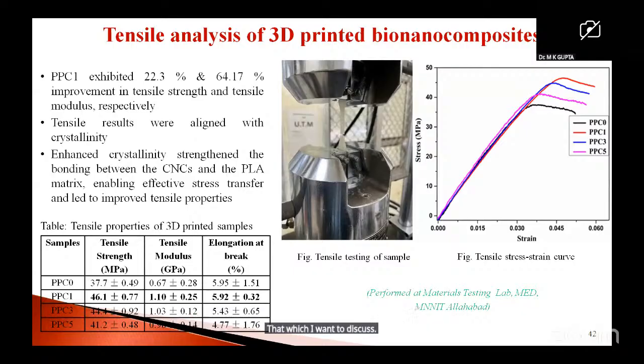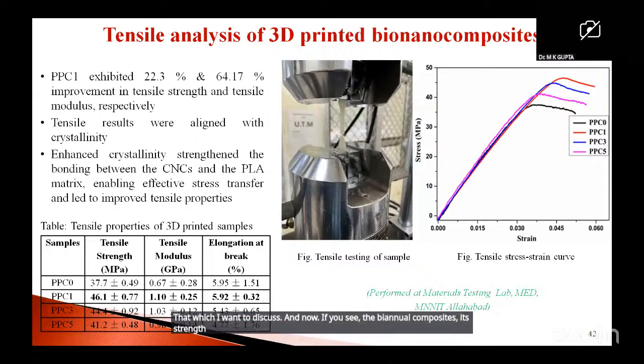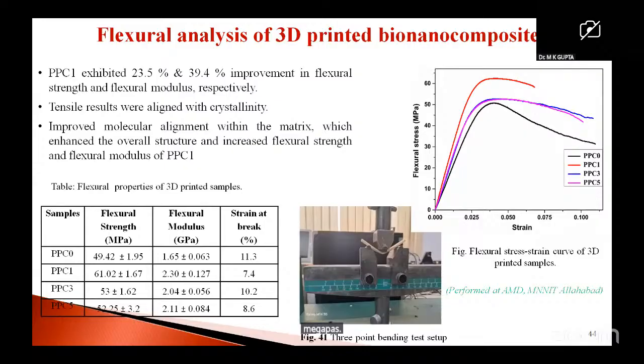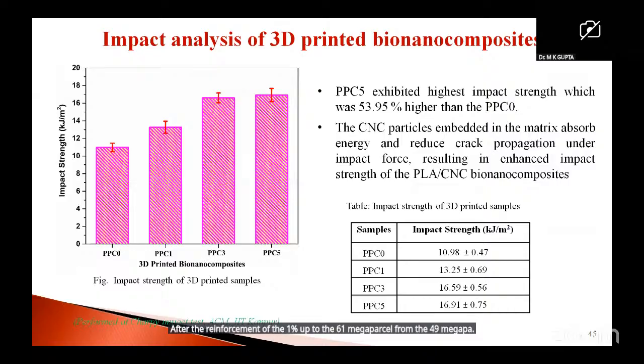Now, if you see the bionanocomposites, for the 1% reinforcement, the strength goes up to 46.1 megapascal. Flexural strength is increased after the reinforcement of 1% up to 61 megapascal from 49 megapascals. Impact strength was also improved from 10 kilojoule per meter square to 17 kilojoule per meter square after the reinforcement of the nanocellulose.